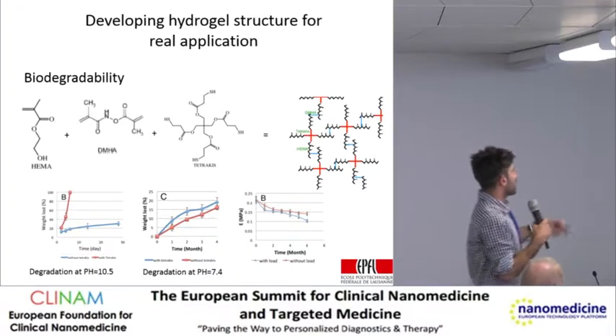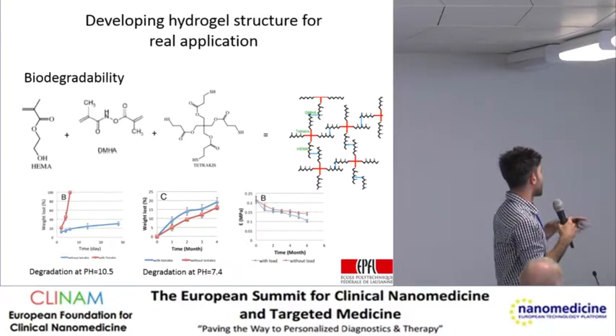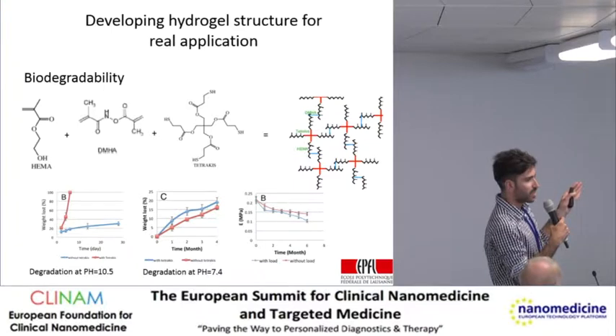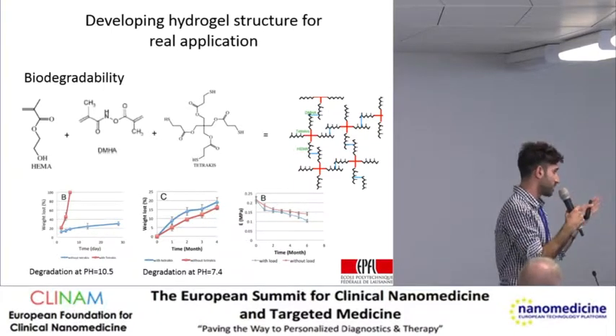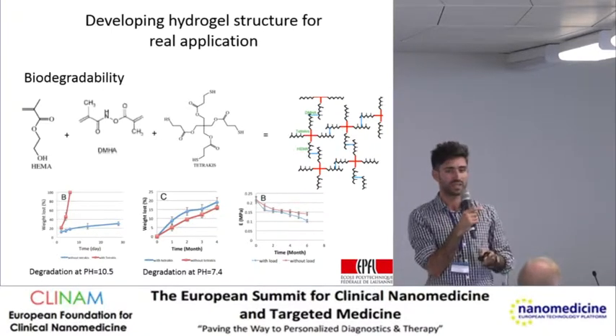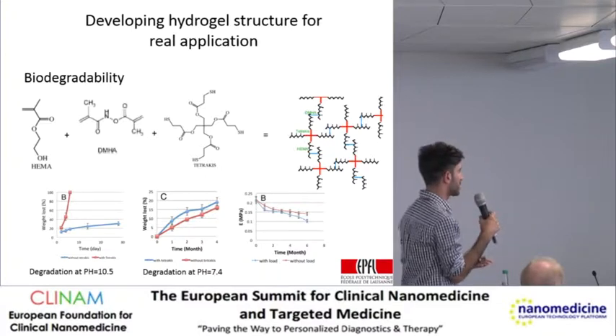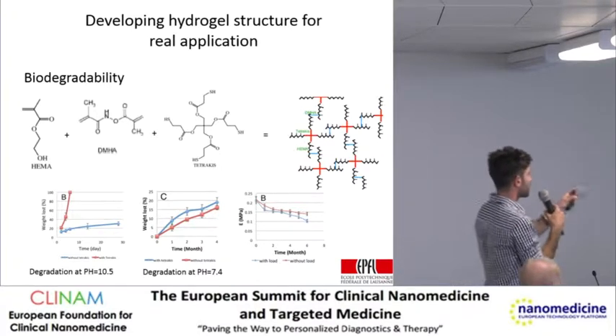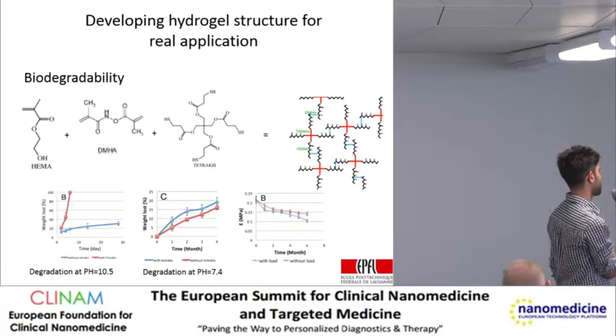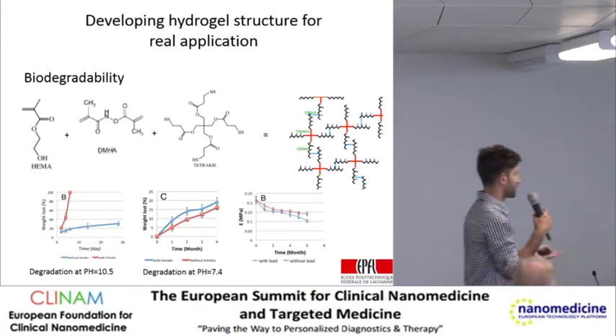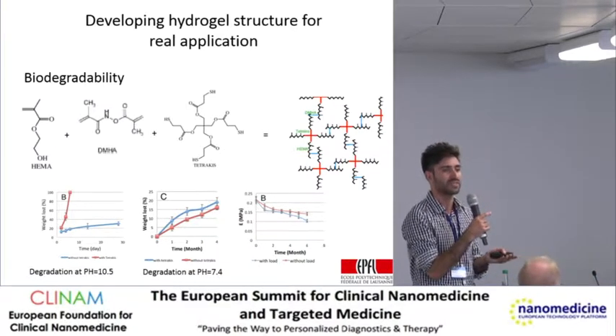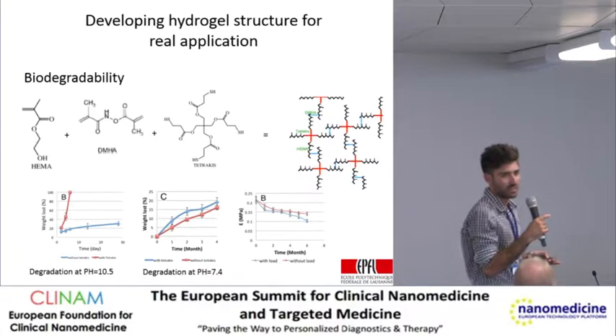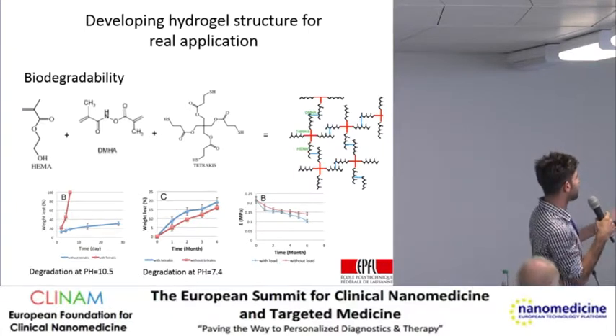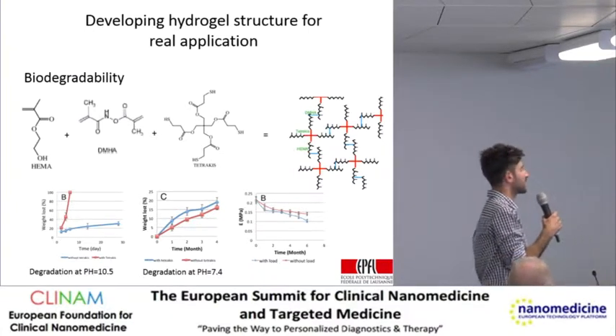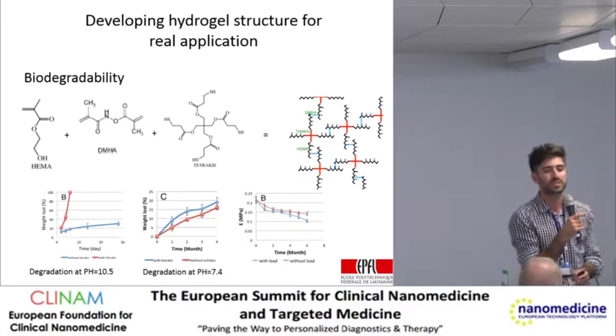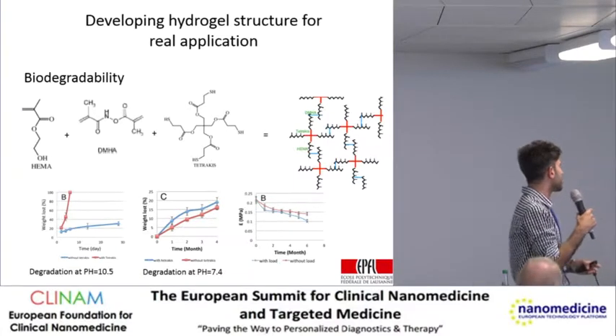But now we have published the first part, and now we should move to the real application. The first challenge was the biodegradability of the gel, because the system that we showed until now was for proof of concept, and it wasn't degradable. For the degradation, it was still a big challenge again, because biodegradable gels are very soft, because normally they use natural cross-linkers. And for that, we needed to find a cross-linker that has exactly the properties of the DMHA that we used.